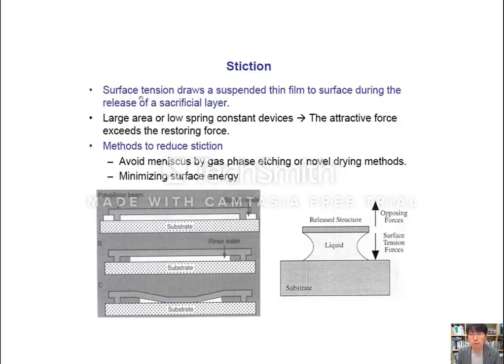Okay, so surface tension draws a suspended thin film to the surface during the release of the sacrificial layer. That's the stiction problem. And a large area or low spring constant device causes the attraction force to exceed the restoring force, which then makes this released structure touch the substrate. Then the question is how do we avoid this stiction problem? Well, you want to evaporate this liquid very quickly or at the same time. So to avoid the meniscus, gas phase etching or a novel drying method is necessary.